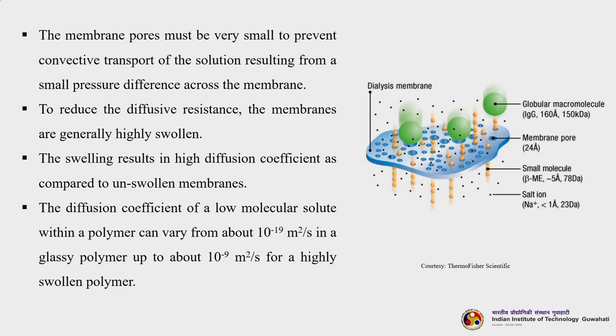Membranes are generally highly swollen to reduce diffusive resistance. Swelling results in high diffusion coefficients compared to unswollen membranes. The diffusion coefficient of a low molecular weight solute within a polymer can vary from about 10⁻¹⁹ m²/s in a glassy polymer up to 10⁻⁹ m²/s for a highly swollen polymer.